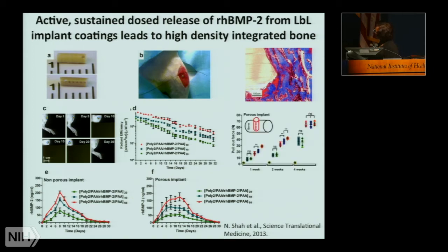On top of that, we did a pull-out test in which we determined the amount of force required to pull the implant out of bone, and we did it at a period of 1 week, 2 weeks, and 4 weeks. Here we can see the untreated control at the bottom. And these implants actually show that there's some bone that is grown near the implant, but it's not integrated into it. And it's very easy to pull these out.